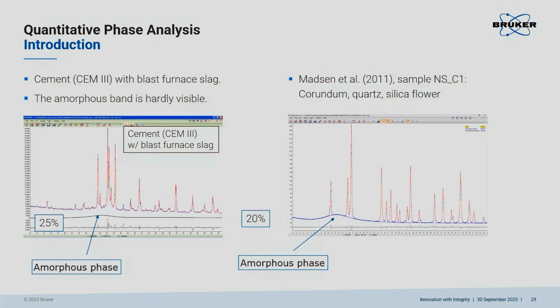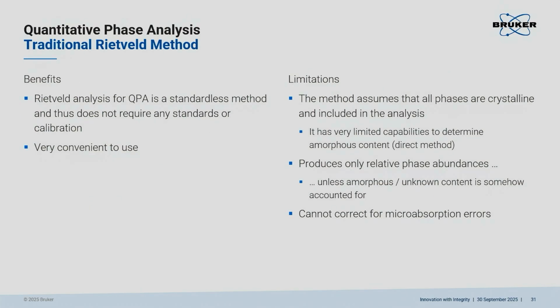So in this case, the direct measurement methods can help you, where you model the amorphous phase. You can also use the indirect method in this case. Here, if there is no visible intensity contribution, then there's also nothing to fit to. Therefore, in cases like here, you will need to do the indirect measurement in case of doubt with an internal standard. Otherwise, you will not be able to do the amorphous phase quantification.